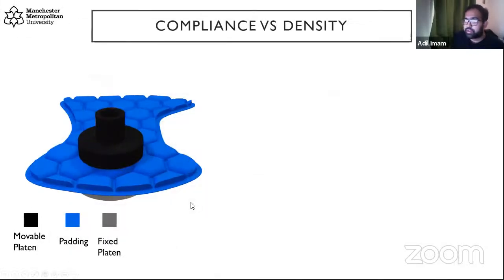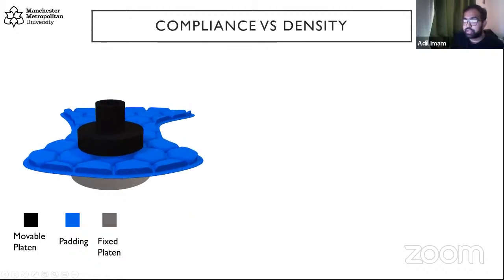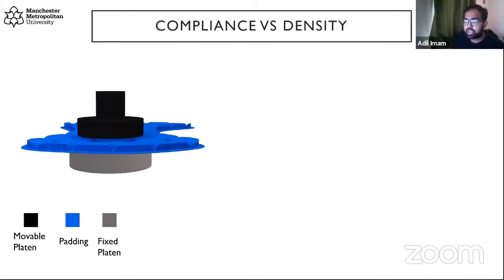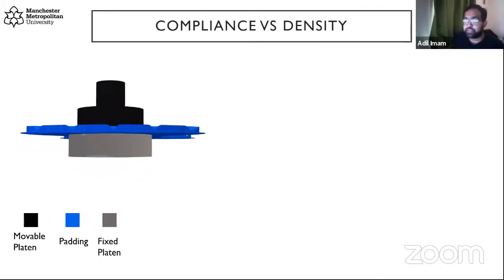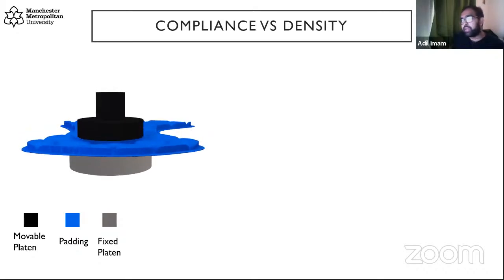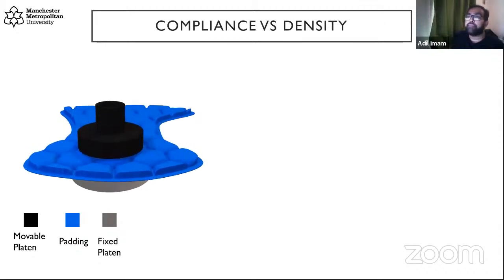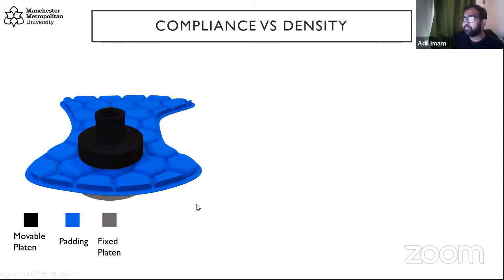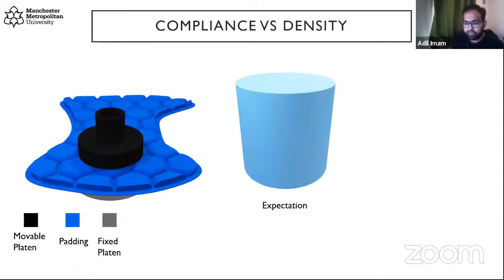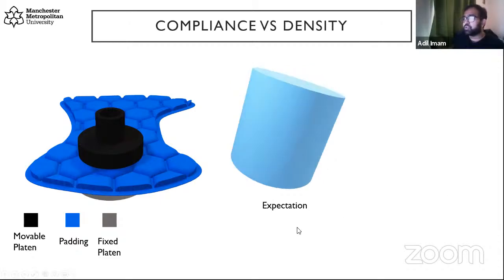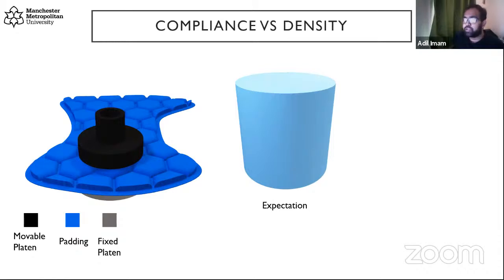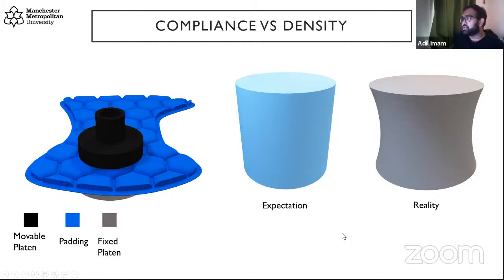Now, we carried out simple compliance testing where we compressed the padding using two flat plates to look at how compliant the material is or how soft or stiff the material might be. And then we carried out some density testing by cutting out paddings from the given padding we have. And you expect to get uniform circular cylindrical structures, which you could calculate the weight, the mass and the volume and get the density of. But in reality, you get structures which are warped cylinders, and measuring them leads to error in density calculations, and higher error in measuring the final density of the material.